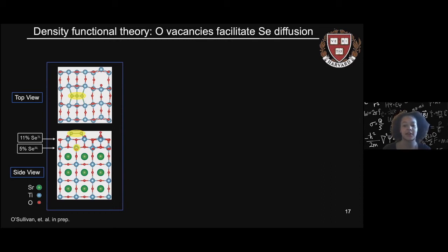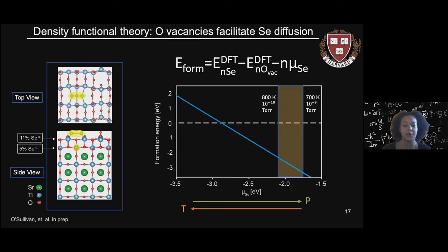So here's our final relaxed structure, and you can see again the crystal as noted by the key here on the left. So in order to employ density functional theory, we ask the question, is this formation where selenium replaces oxygen, specifically at these percents, energetically favorable? So we define the formation energy of the entire process here, and we then find the experimental conditions based on the selenium partial pressure and the substrate temperature.